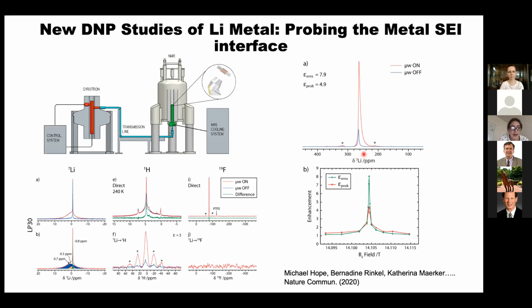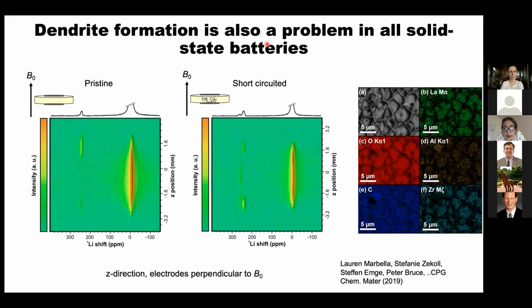But what we did then, which I think is where it's exciting, is we transferred directly from the lithium spins of the metal to this passivating layer to see what the protons were doing and what the fluorines were doing. And we were actually able to look at this lithium metal SEI interface. So not the interphase, but actually that interface, to understand that chemistry. That's something we're really trying to push at the moment.